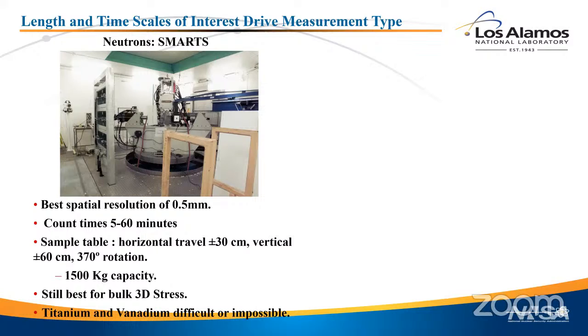So one of the things neutrons give you very well is a nice statistical average of all the grains. One of the things it doesn't give you is spatial or time resolution. A measurement at the neutron beam will take me anywhere from a minute to an hour. Dan's neutron beam might do a few in a couple seconds range, but that's about as fast as we're going to go with neutrons.